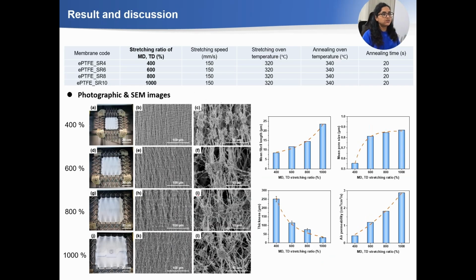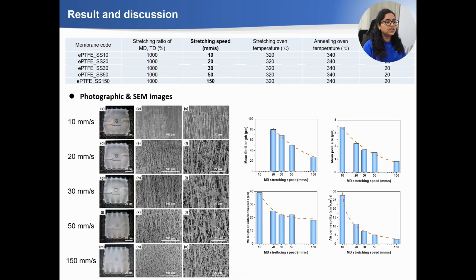So we use different parameters like the stretching ratio, and we change the stretching ratio from 400 to 1000 percent. With the different stretching parameters, the fibril length and mean pore size of the material increased, thickness decreased, and permeability also increased.